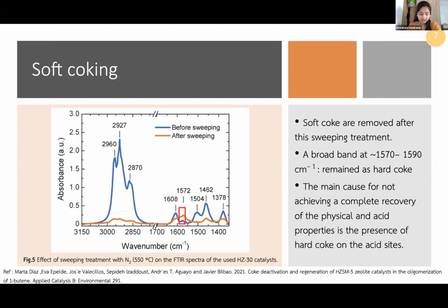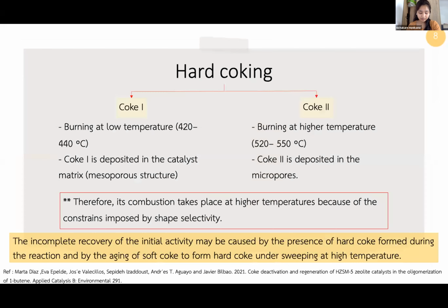An interesting band is observed after sweeping, characteristic of more evolved polycyclic aromatic compounds that remain as hard coke. The main cause of the incomplete recovery of the physical and acid properties after sweeping is the presence of hard coke on the acid sites.